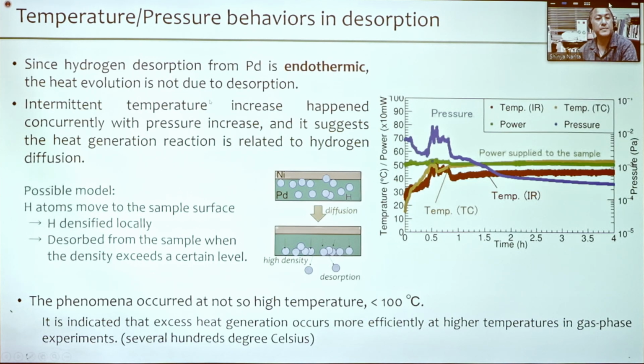Okay, so since the hydrogen desorption from the palladium is endothermic, the heat evolution is not due to the desorption heat. And some intermittent temperature increase happened concurrently with pressure increase, as I said, and it suggests the heat generation reaction might be related to the hydrogen diffusion. So now, for example, the following diffusion model is possible.